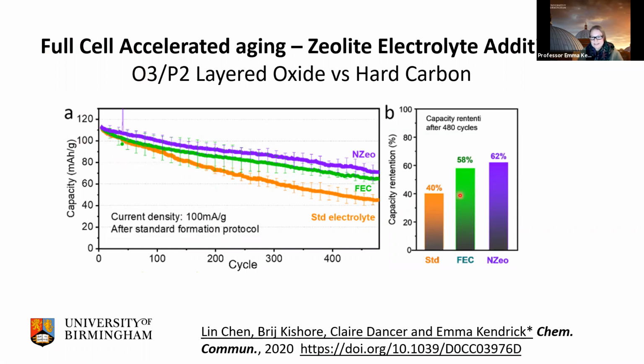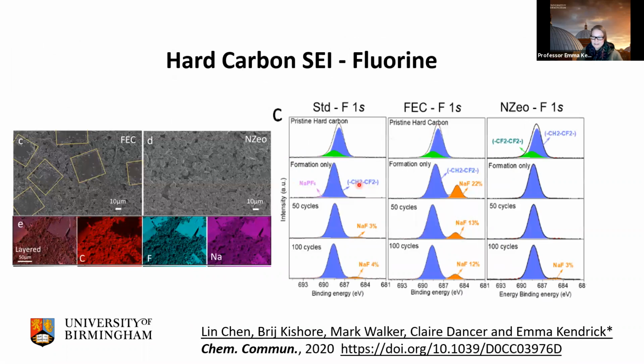We also compared it to what is normally added to a standard electrolyte for sodium ion, which is FEC. And it's thought that the fluorine content in the FEC helps to form a stable interface layer. And from some work that we did, we actually showed this to be also counter to what we actually observed.